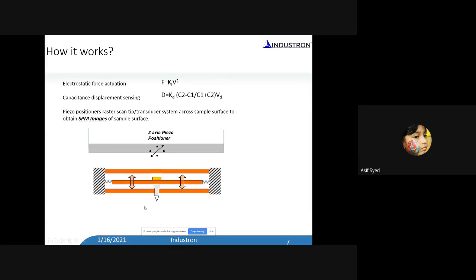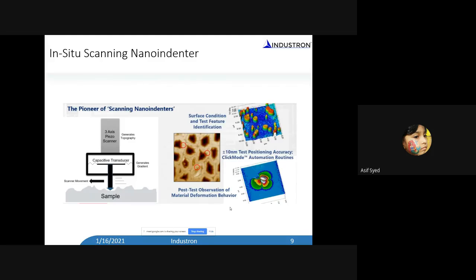Now let's say the tip is in contact with the sample surface, and when you scan with the piezo, the tip slides on the surface, and because the spring stiffness is so low, the tip will move up and down with the surface roughness, like a profilometer. Now you can record this profile, and with it you can construct the 3D map of the surface. That is how we can see what is on the surface. That's what I'm showing in this particular slide. There are a couple of images that you can see. The first image is a wood cell, and you can see the cell wall around the cell, and tiny indents around the cell wall.